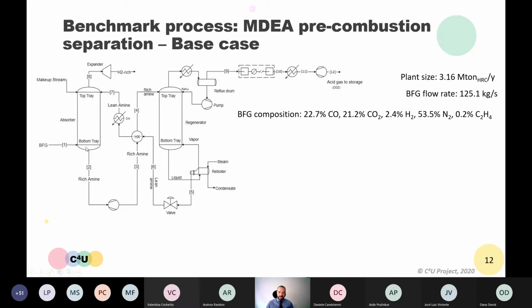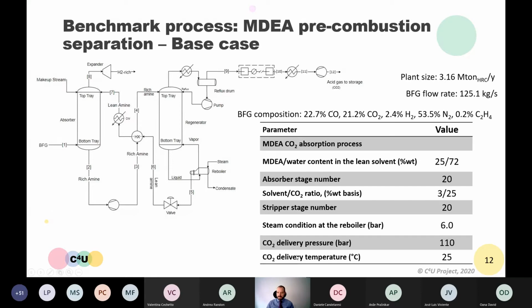So this is an MDEA solvent-based process where the BFG can be purified from CO2, from which we can get our hydrogen-rich gas. And at the same time, the CO2-rich amine is then regenerated in a desorber column by using low-pressure steam. You can see here our BFG composition and the main operating conditions. What is worth mentioning at this stage is that low-pressure steam at 6 bar is used for regeneration. CO2 is delivered at 110 bar. And basically for the base case, which is the one with the mild capture, we are expecting to have a decarbonized fuel, which will still have all the CO, a very limited quantity of CO2, hydrogen, nitrogen, and other components, including water.